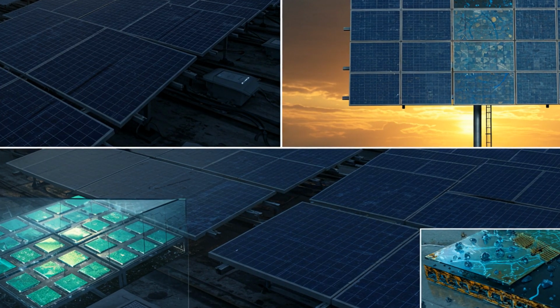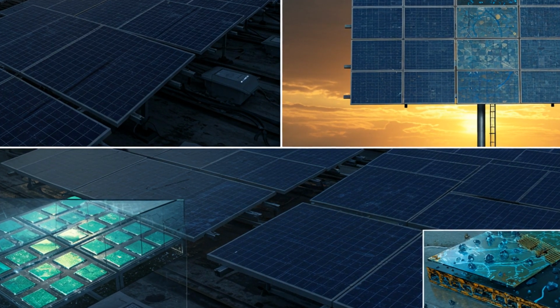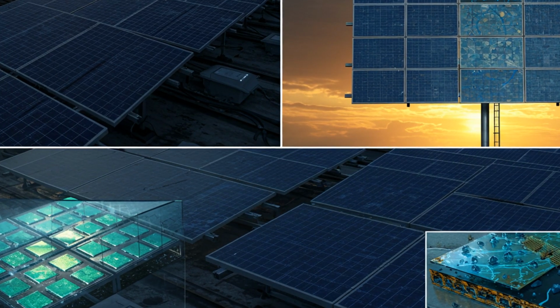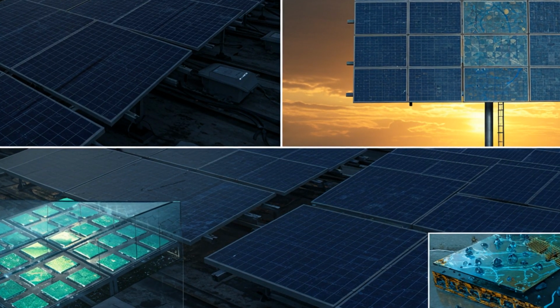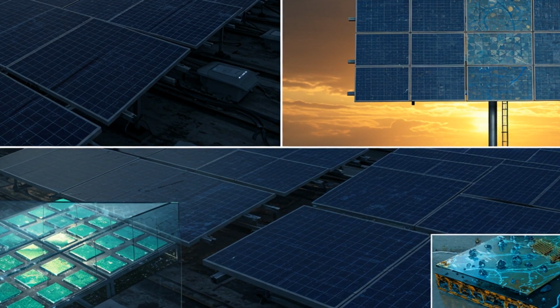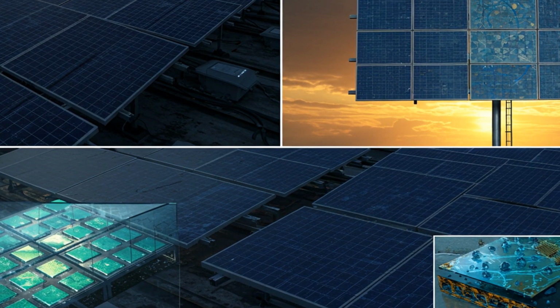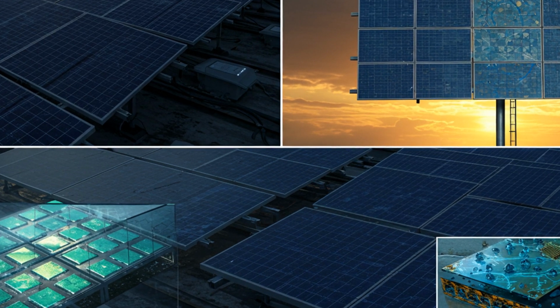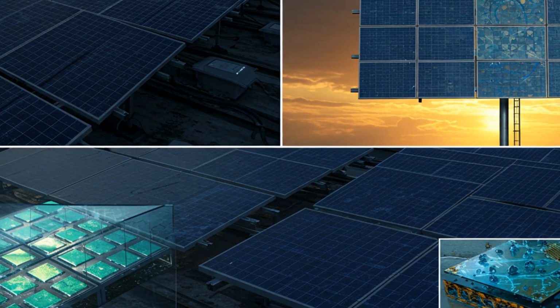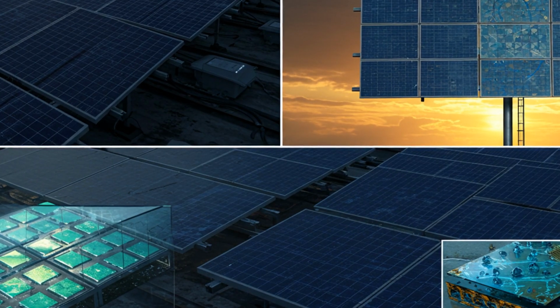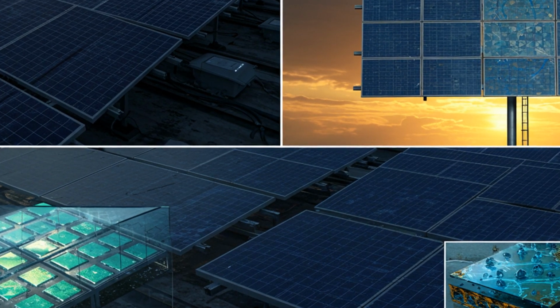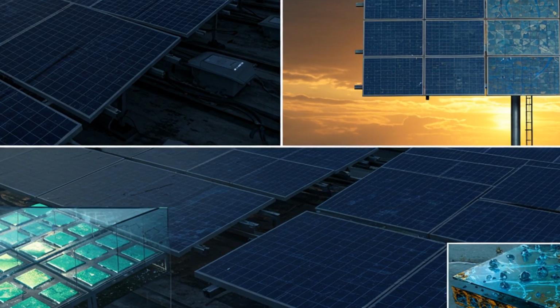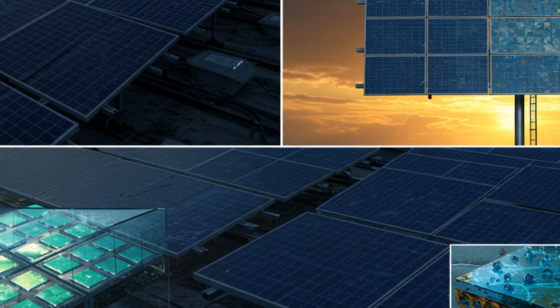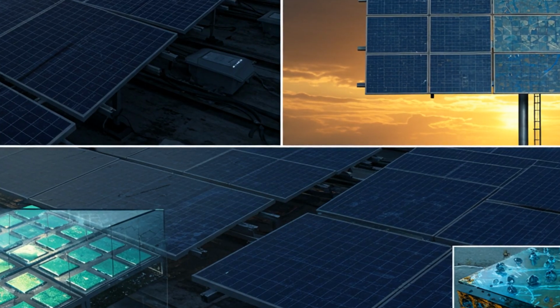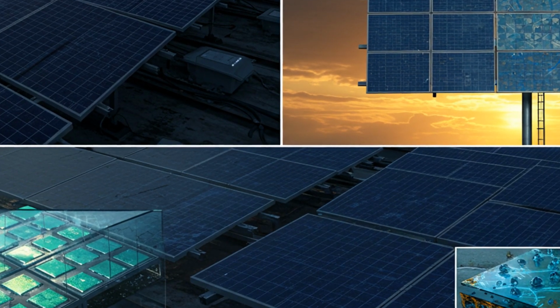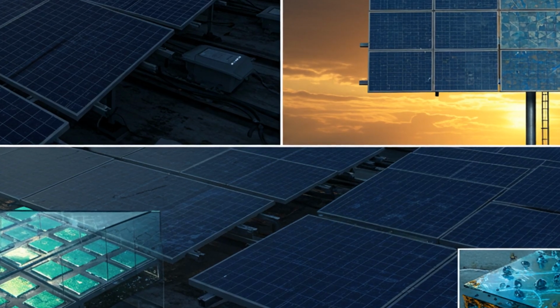Recycling and end-of-life are also engineering problems. Recovering glass, aluminum, and silicon requires thermal or mechanical separation processes and is becoming a standard part of the life cycle. Meanwhile, cell technology continues to evolve. PERC, heterojunction, TOPCon, and tandem designs push efficiencies higher by changing passivation strategies, adding thin films, or stacking materials with different band gaps. But the core logic remains: transform ordinary atoms into a lattice that captures photons, control where carriers go, and extract usable current without loss. From sand to sun, the journey is a cascade of heat, chemistry, and microscopic precision, engineering that turns light into power.